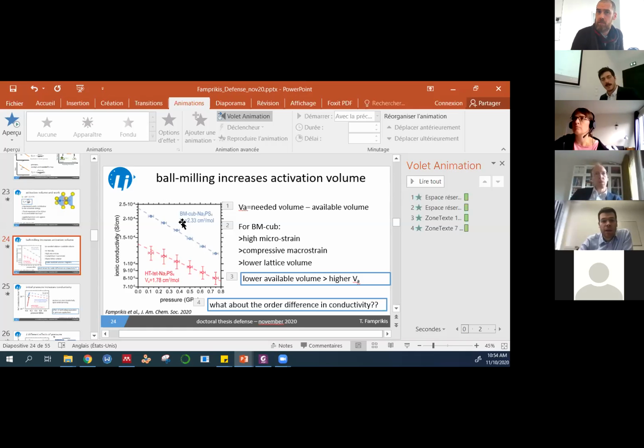Can I quickly jump in here? You can measure defect concentrations in ionics. This is done in ceria, for instance, via dilatometry. It's just that in these diphosphates, it's really difficult to make a very dense bar-shaped sample, like 100% dense, and put that in a dilatometer. But in principle, this is doable. The oxide ion conductor field has done this over decades. I'm honestly not very familiar with this, so I don't know if this is the time to discuss it, but I'd be very interested to hear about it. But Theo, I'm also a strong believer that diffraction can dig up some details.